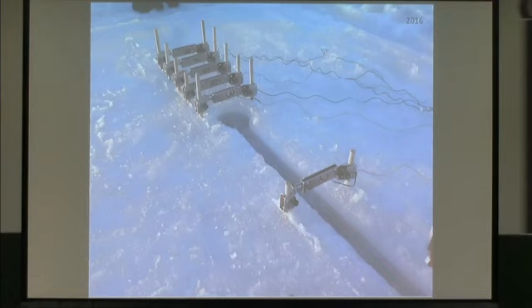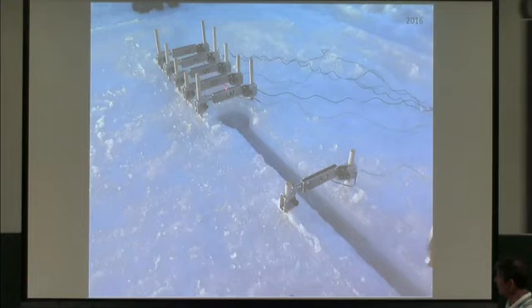Another important thing was this device we had developed for measuring the crack opening when it starts, when you get the stress out here and you start running forward with the crack. So a neat device here installed, mounted on wooden sticks in the ice and frozen in, so it was quite stable.